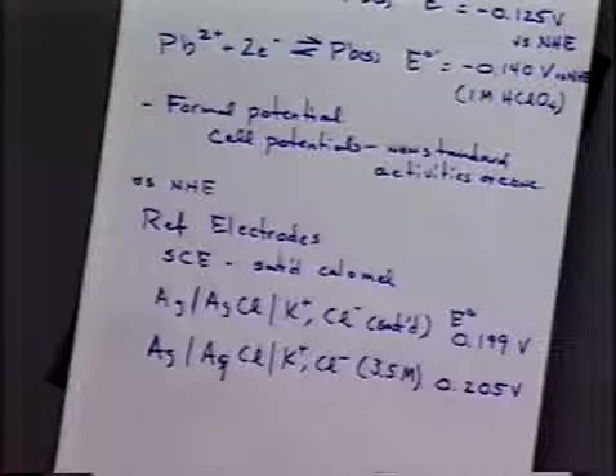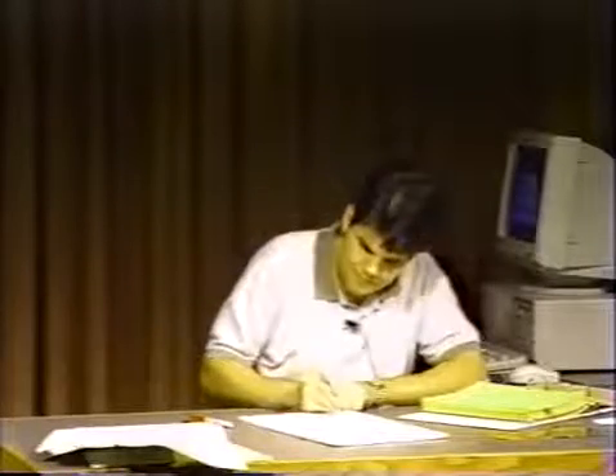So you can see that difference in 3.5 molar KCl solution and the saturated solutions counts to about 6 millivolts of potential. Not a huge amount in analytical work, but in fact for precise potentiometric measurements it's very important. Why would we care? Why wouldn't you use saturated systems, for example? That's an easier system to prepare and maintain. All you have to do is have a silver chloride or potassium chloride solution that's in contact with a potassium chloride solid, and you'll have a saturated potassium chloride system. But actually it turns out that there's good reason for using the 3.5 molar potassium chloride solution.